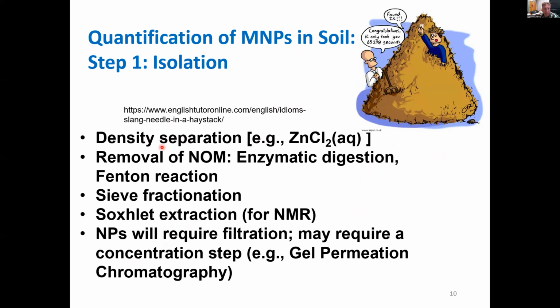If we want to isolate, because we really have a needle in a haystack situation, we can do density separation, for instance. Works very well. Often we have to remove the corona material. We can do oxidation type reactions or enzymatic digestions. Fenton's reaction being oxidation. We may need to do sieve fractionation to get particles at different sizes. And also Soxhlet extraction is needed.